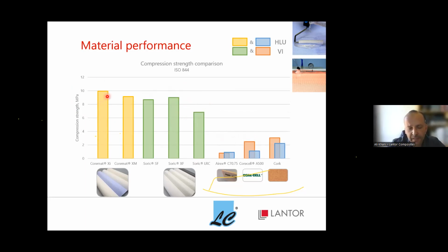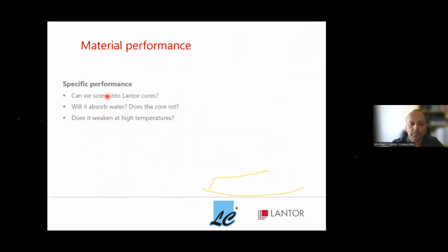The reason that our cores behave very well in terms of mechanical properties compared to the foams is that the Lantor core allows the resin to impregnate through it. This resin impregnates through the core and makes bridges between the top and bottom skins, which contributes to a lot of the mechanical properties.